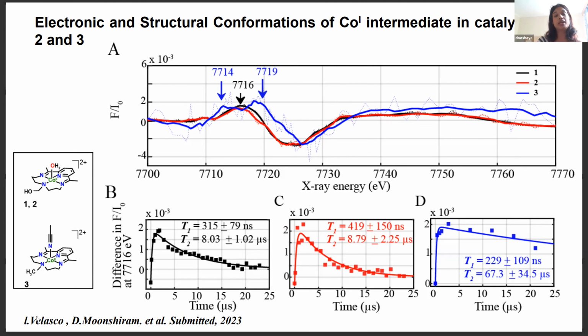The methyl group is located slightly further away from the cobalt metal center, whereas the hydroxymethyl group with the hydrogen-containing amine can actually promote hydrogen evolution, so it can act as an H-H bond relay and facilitate the protonation of the cobalt-1 intermediate. This was interesting because according to the different hydrogen evolution pathways, cobalt-1 is usually protonated to form the cobalt-3 hydride species, which can react either through homolytic or through heterolytic pathways to evolve hydrogen. So the faster protonation of the cobalt-1 shows that this amine substrate does play a very important role in promoting catalysis.